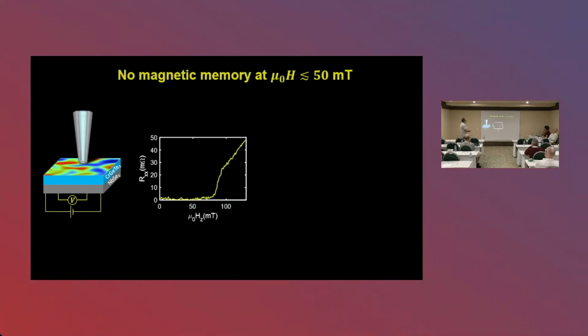We don't need to go all the way to zero field. So this is when we go to zero field and go up again. We can stop, go down, and stop and start to go up here. It's the same thing. And you really need to stop in the middle of this voltage state to go up on the other branch. So basically, as soon as we start seeing those domains, the magnetic sample forgot where it came from.